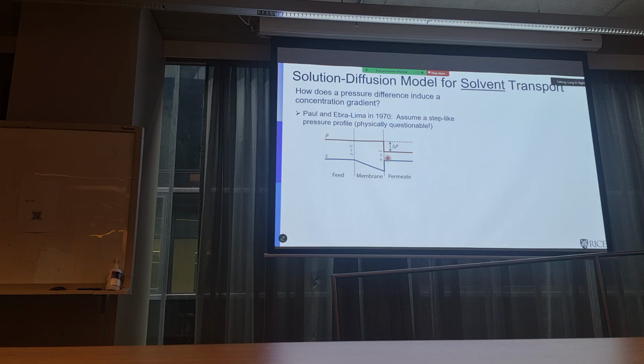Then they set up an equilibrium between the liquid phase in the permeate and what is happening inside the membrane. Using Fick's law, etc., they developed the equation for the concentration of water just inside the membrane. C_L^m is just inside the membrane before going to the permeate. And you see this relationship with the pressure in the influent, P0, and the pressure at exit, PL.